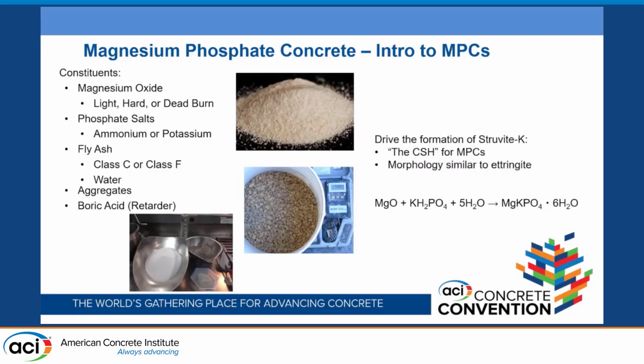And then the whole point, with UHPCs or whatever else, is you want to drive the formation of CSH. So for magnesium phosphate concrete, you're trying to drive the formation of struvite-K. I called it the CSH for MPCs, but its morphology is similar to ettringite. And then there's just the chemical process. You've got your magnesium oxide, your potassium phosphate, which is actually a fertilizer, then you have water, and then there's your struvite-K formula.